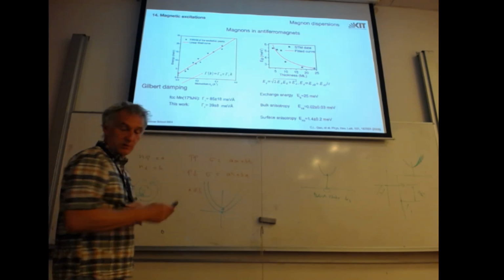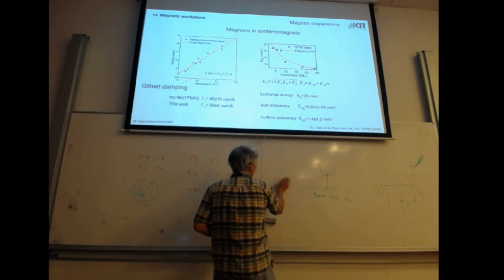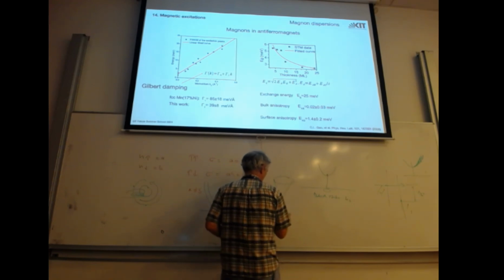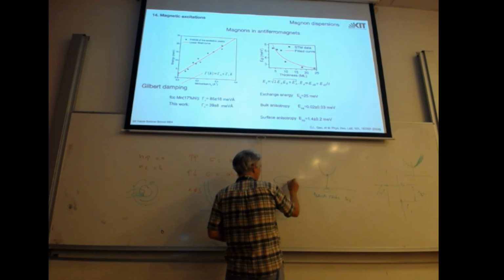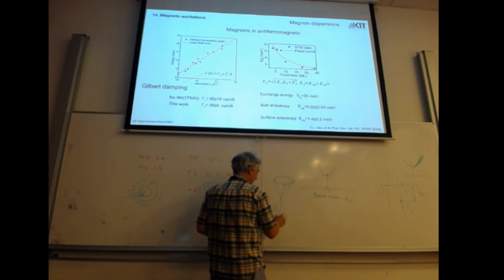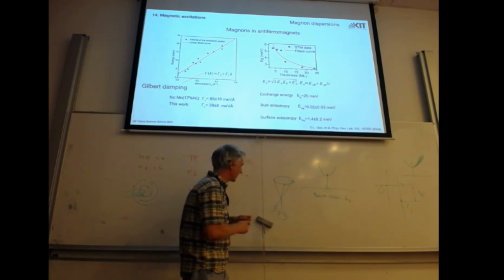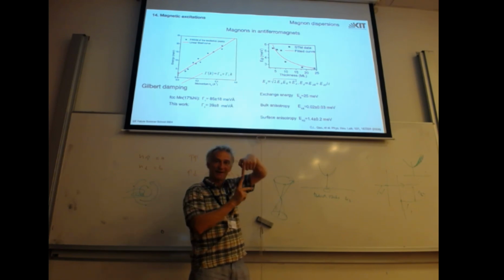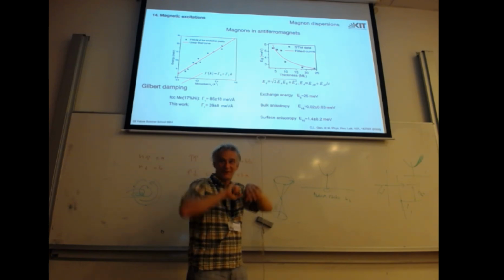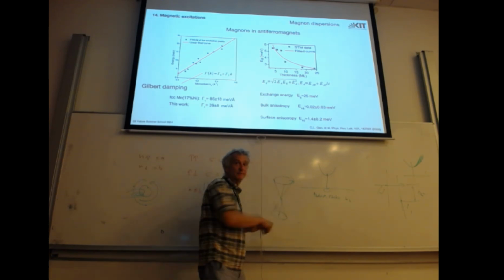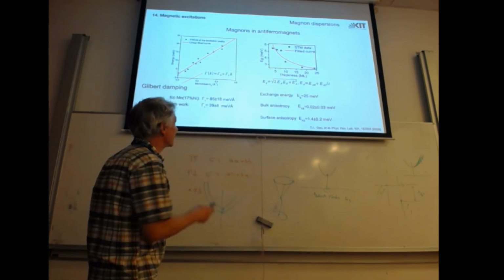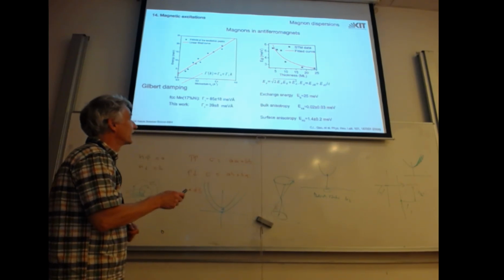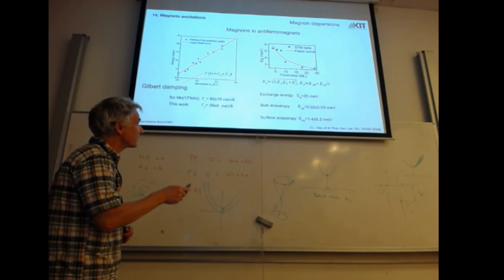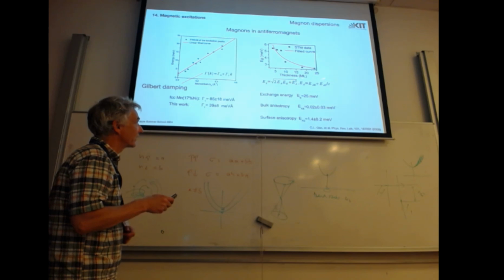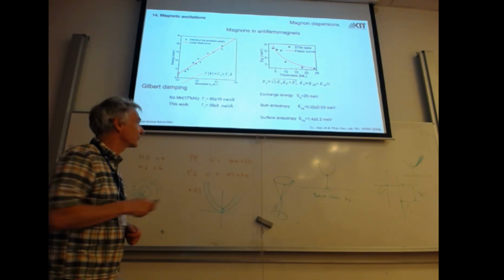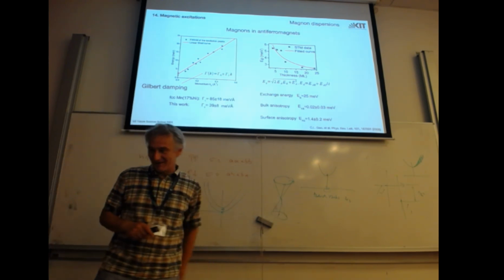Okay, now let's go to magnons. So magnons in antiferromagnets. There's a precessing spin here. There's a precessing spin here. But you have to be careful, they are not precessing collinear, but they have opposite rotation senses. So there's an exchange interaction happening. They don't stay parallel. And that means our gap is larger. And this is the energy gap. We measure it as a function of thickness. And it follows a 1 over thickness rule. So that means we have volume anisotropy and surface anisotropy in this system. That's this side remark.